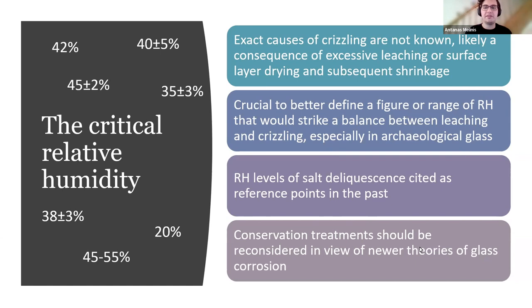So arguably the main factor governing glass deterioration post-excavation is the ambient humidity. And many scholars have tried to pinpoint the optimal range that would balance out leaching and drying in an effort to stall it, with just a few proposals listed on the left, but even the deliquescence points of various salts that form on or within the glass have been put forward as points of reference, because they would probably not be attracting moisture below their deliquescence values. However, these must be reconsidered in face of newer evidence.